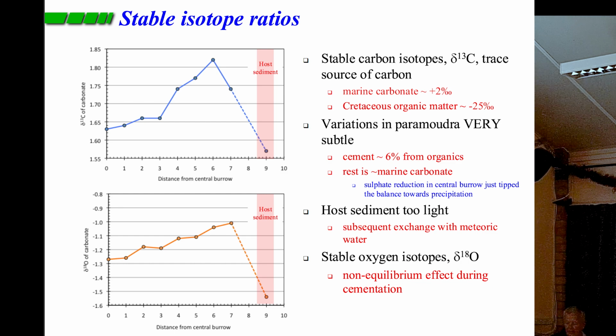So the net effect, we can say that most of this carbonate is actually chalk which has been redeposited. Only a small percentage of it, about 6%, is coming from the decay of the organic matter itself. And that comes as a surprise. We were expecting to see very light isotopes there, but we don't. It's rather like if we have bacterial sulfate reduction attacking the organic matter, that's just tipping the balance. The bulk of the carbonate is coming from around the area, and probably from where we're dissolving carbonate to form the flint.